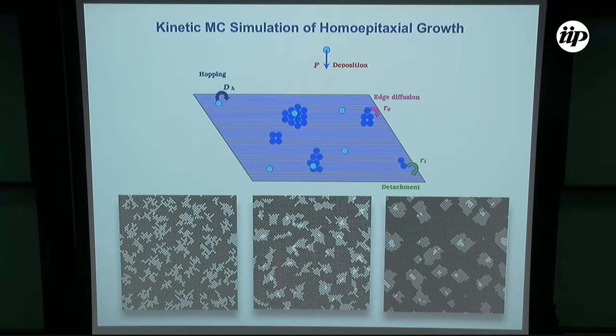Here's the Monte Carlo simulation. It is different from the equilibrium simulation in a sense that you don't have the detailed balance that you have there, and the probabilities of moves are dependent on the initial and final conditions rather than the kind of Metropolis algorithm that David was talking about. So in a basic simulation, what you do is you deposit atoms onto a substrate, and here are different simulations. What's the difference between them is the speed of deposition. If the deposition rate is very high, the atoms don't have that much time to move around, so they make very fractal islands. They freeze almost as soon as they hit another island. But if the deposition rate is slower, there is time for atoms to diffuse, and so you make more compact islands. These white atoms are already deposited into second layer, third layer, and so on. So you can imagine these three-dimensional islands are forming.